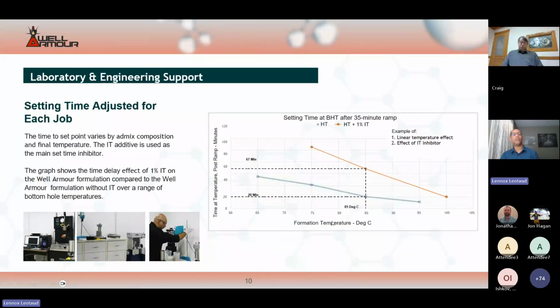And the set time for Well Armour is pretty predictable. In this example here, this is a Well Armour HT slurry without inhibitor added, and the red line is a Well Armour slurry with 1% inhibitor added. You can see that as the temperature increases for both slurries, the set time reduces, and zooming in here at the 85-degree temperature, you can see the slurry that doesn't contain inhibitor gives you a 20-minute set time, and at the same temperature, the slurry with 1% inhibitor gives you a 67-minute set time.